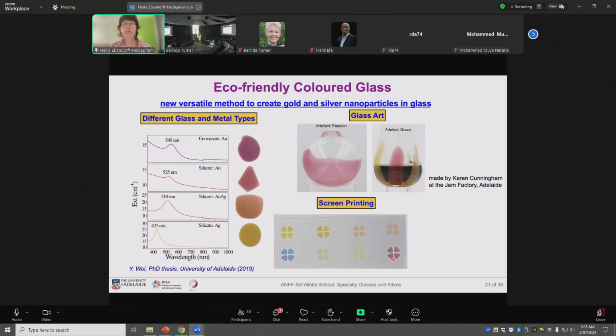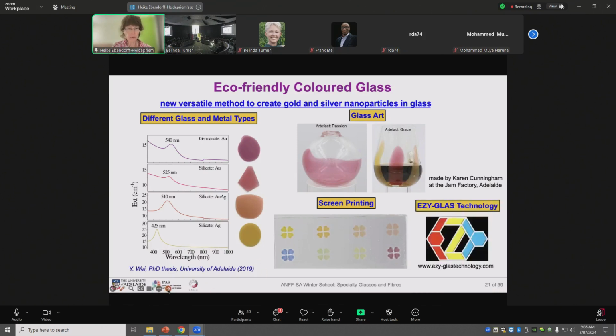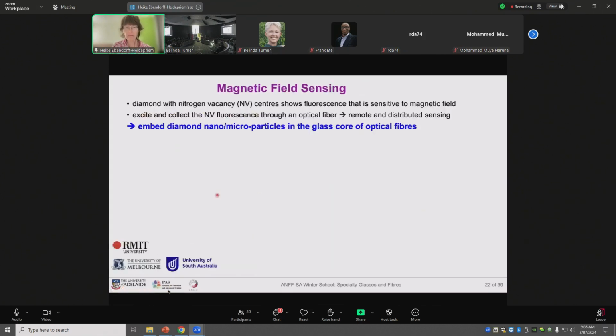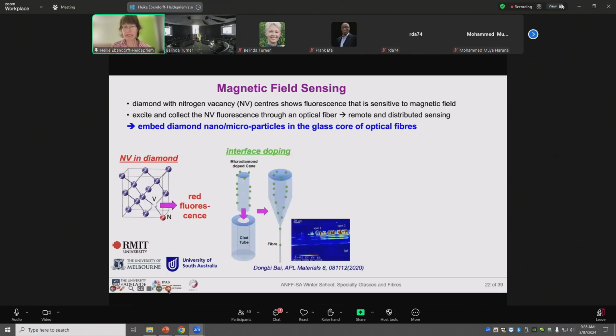Another example is magnetic field sensing. The key point here is nitrogen vacancy centers in diamond. They have a fluorescence in the visible, in the red, and this fluorescence is sensitive to magnetic fields, and therefore, by looking at changes in this fluorescence, the magnetic field intensity can be inferred.